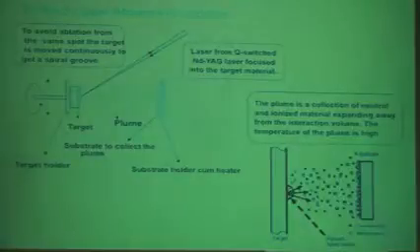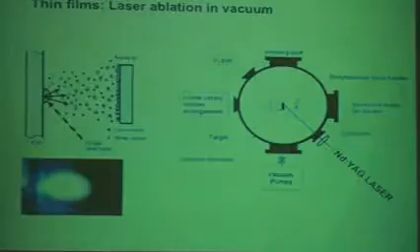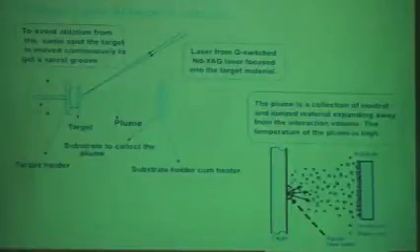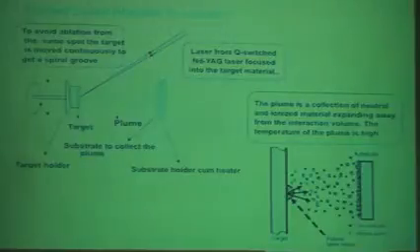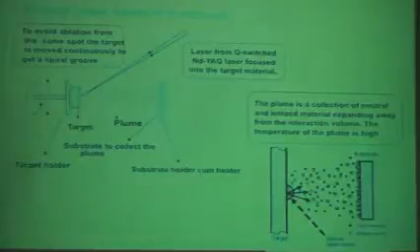Good thing about laser is it just doesn't care what material it is evaporating. It can be hard tungsten, it can also be a gentle polymer, organic substance. It doesn't care at all. Basically you need to play with the laser fluence in order to not do certain things. If you're working with tungsten kind of refractory metals and materials, some oxides, then you need to increase the laser fluence. But if you are working with gentler materials, probably you need much less fluence.